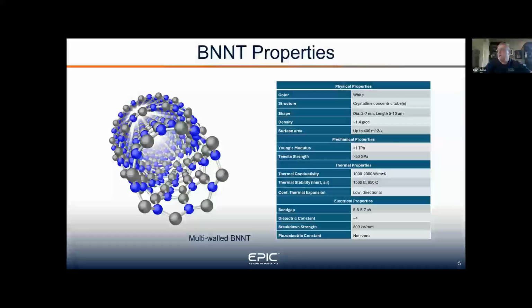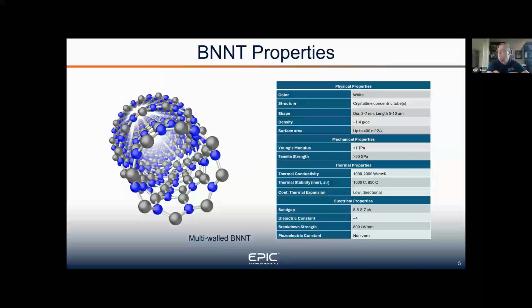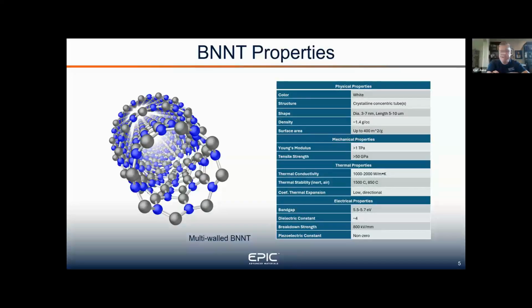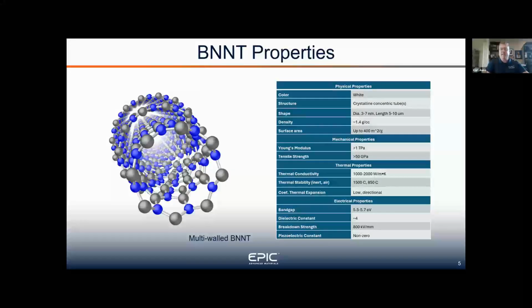BNNT properties, they're white. Again, crystalline concentric tubes. They're somewhere in between 3 to 7 nanometers in diameter and about 5 to 10 microns long. Their density is about 1.4 grams per cc. What separates them on the mechanical properties is the incredible Young's modulus strength and the tensile strength. And I'll talk a little bit more about the thermal conductivity.